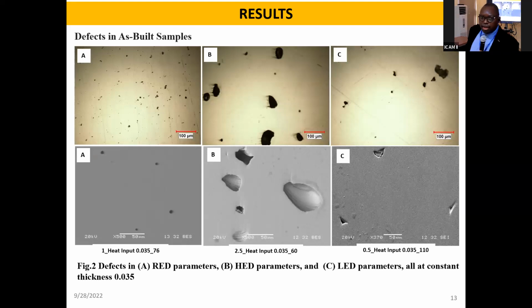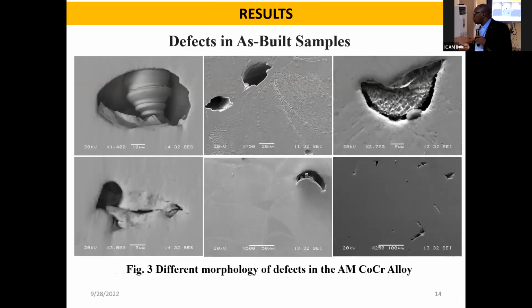This is analyzing the optical image of the as-built samples, and it has a lot of differences. We can see from the analysis that the recommended energy density has the lowest, the high energy density has the highest, and the low energy density is intermediate. This is using standard recommended to high energy density. You see the nature of it, especially, they are incomplete. Can you see that?